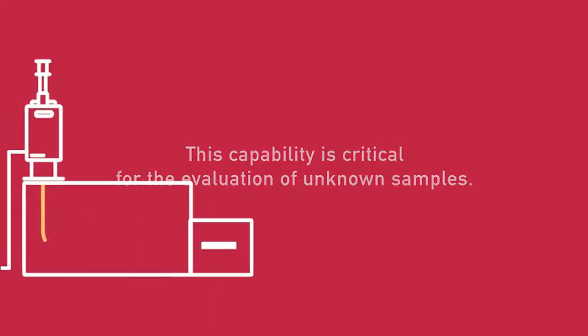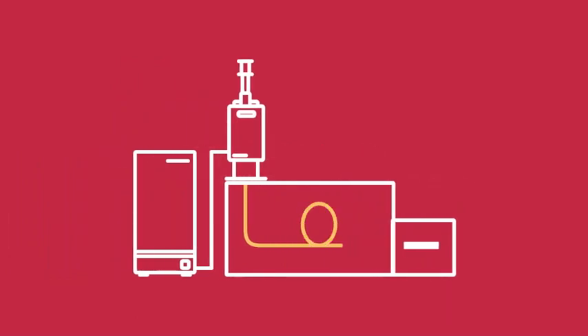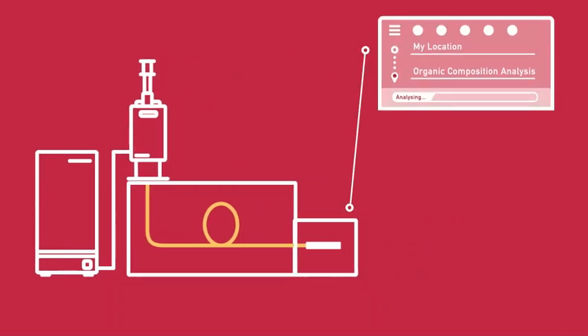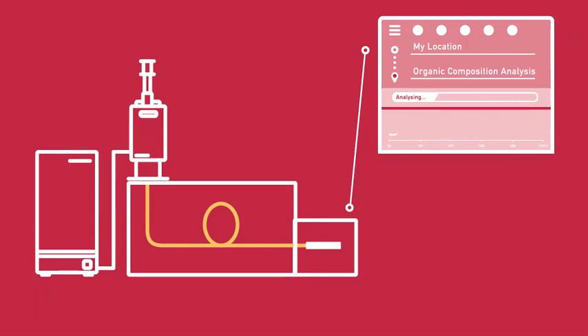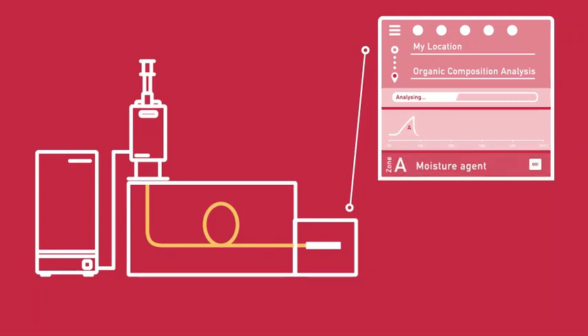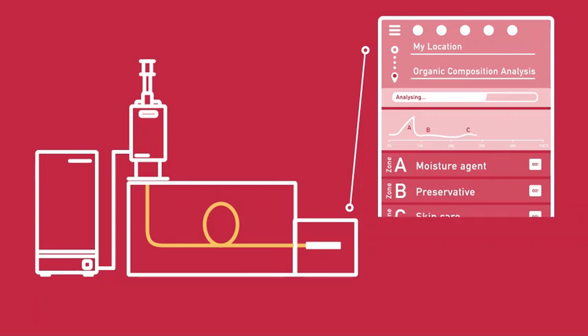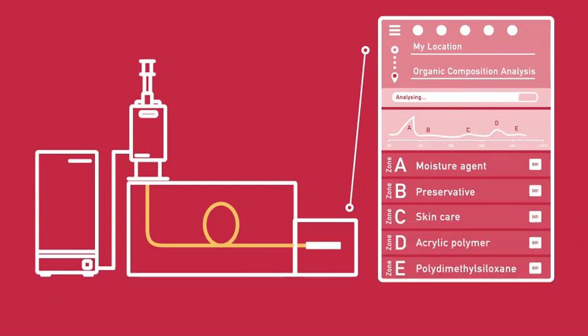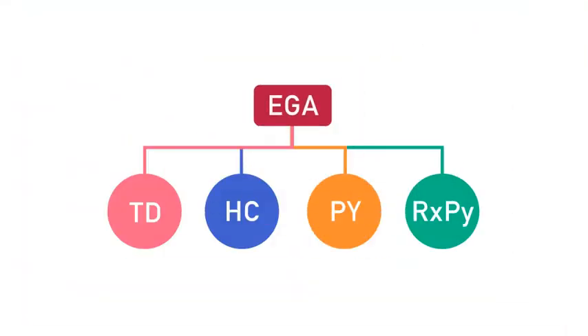To perform EGA, a short and deactivated tube connects the GC injection port to the gas chromatography detector. The sample is dropped into the multi-mode pyrolyzer's furnace, which is set at a relatively low temperature. The furnace is then controllably ramped to a much higher temperature. Compounds evolve continuously from the sample as the temperature increases and are directly transferred to the detector. A plot of detector response versus furnace temperature is then obtained. You have just completed your first step on your journey to the land of answers.